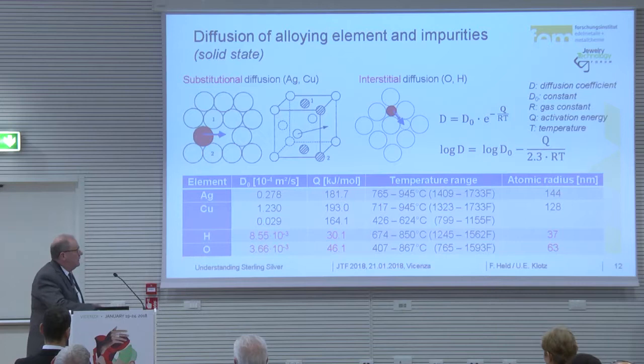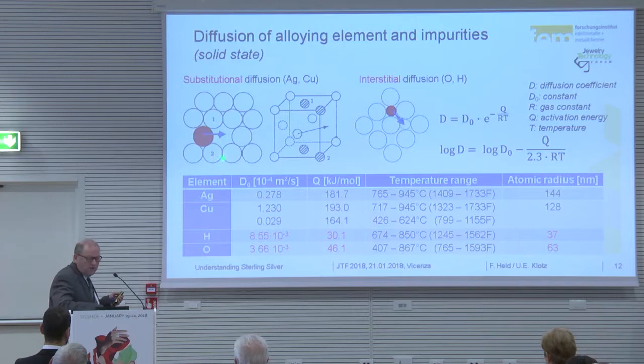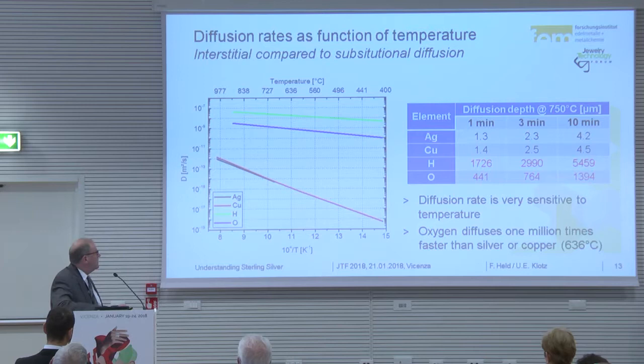Here we have the diffusion of two things. We have substitutional diffusion, that's for the metals. Here this is silver, this is copper. Copper has to change the place with silver, so the diffusion is slower. If you look at oxygen and hydrogen, it is interstitial diffusion, so it goes between these elements and can go much faster, because oxygen and hydrogen have a much smaller atomic radius. This makes it possible to go fast.